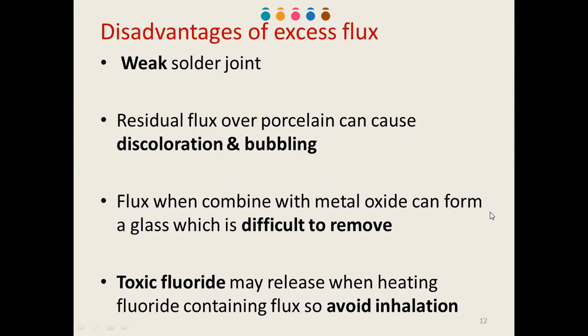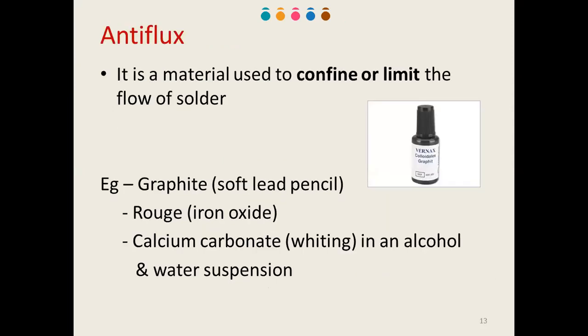Now, whenever you are applying the flux before doing the soldering procedure, whatever the technique used, it is very, very important that you use a minimum amount of flux. Okay, so if the flux amount is increased, what will happen? The excess flux will remain trapped within the filler metal, and it will cause a weakened joint. Second, if you are using excess flux, the residual flux remaining over the porcelain can cause discoloration and bubbling. Third, flux when combined with metal oxide can form a glass which is very, very difficult to remove. And if you are using fluoride type fluxes, toxic fluoride may be released when heating fluoride containing fluxes, so you will have to avoid inhalation. That means you will have to take precautions whenever you are using fluoride containing fluxes. So a minimal amount of flux should be used.